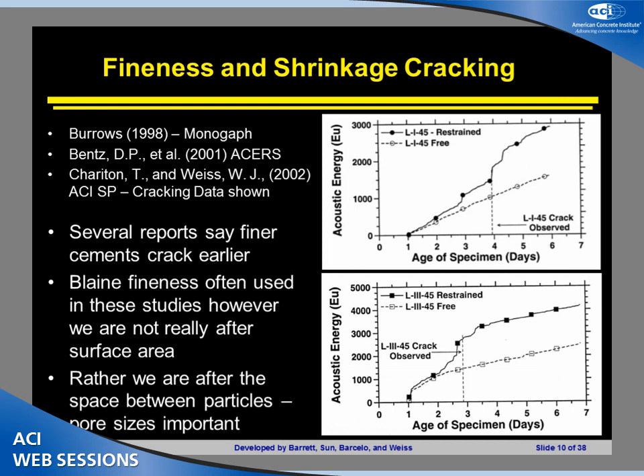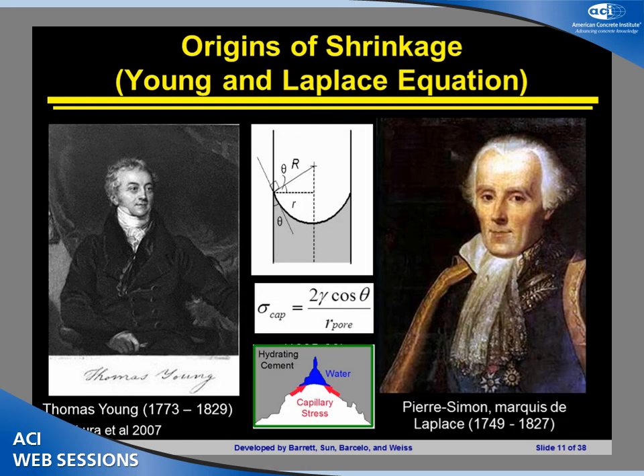This is something that you can see if you go about this with the conventional OPC types of mixtures. The Blaine fineness is often used in this study, and that's often the single measure that we've got. I think one of the things that is going to become really evident as we look at this is that Blaine fineness gives us a number, but may not give us the complete picture of how these materials behave. So here's a typical OPC that's ground finer, and we see the age of cracking moves from 4 days down to about 2 days. But again, remember, that's a conventional OPC system where all that's been done is the clinker is ground more and more fine.